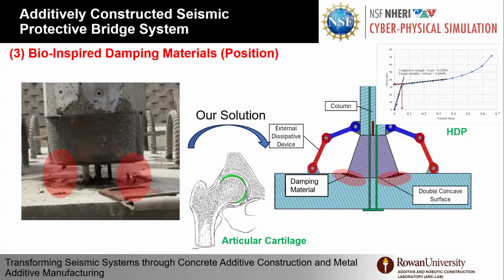And one example here, as I mentioned, high density polyurethane, where we have very low stresses, almost 30 psi, similar to the tire pressures that we have, but it maintains this force based on the vertical strain for up to 45%.